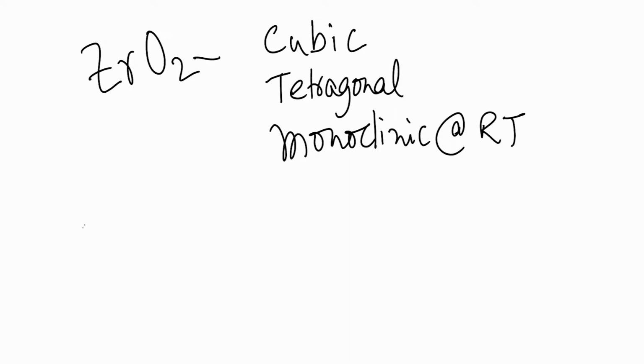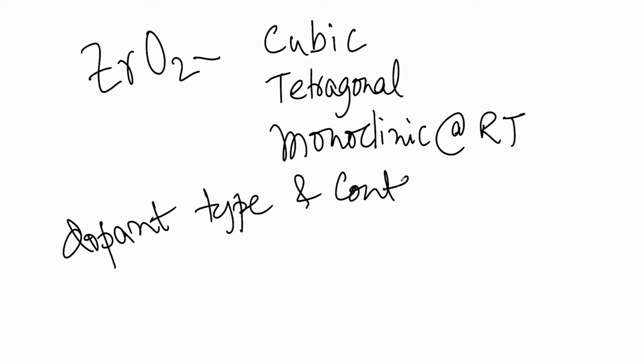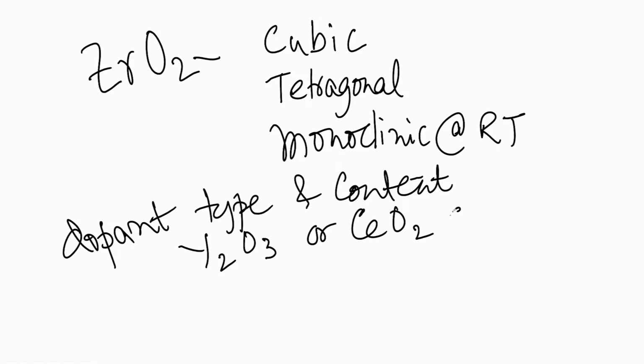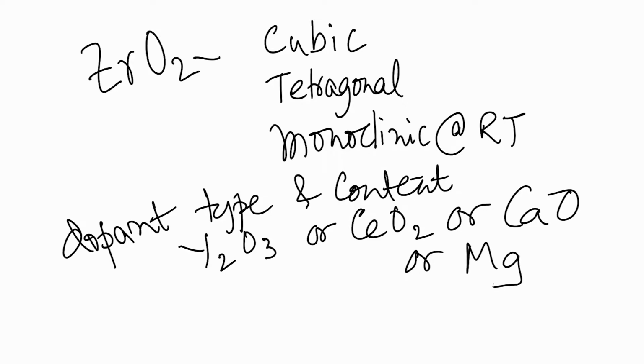Now, depending on the dopant type and content. What are the dopant types? Dopant type can be either yttria or ceria or calcium oxide or magnesium oxide. These are the different oxide dopants; it can even be niobium oxide, niobium doped zirconia is also possible.